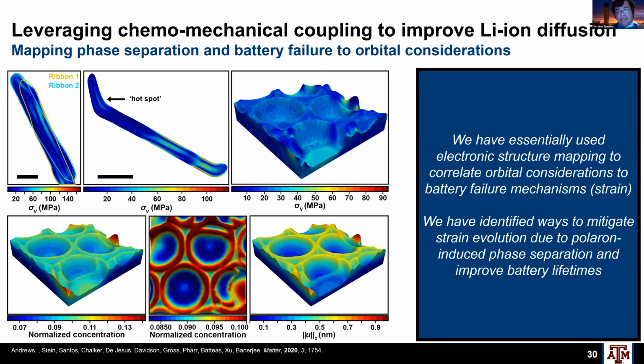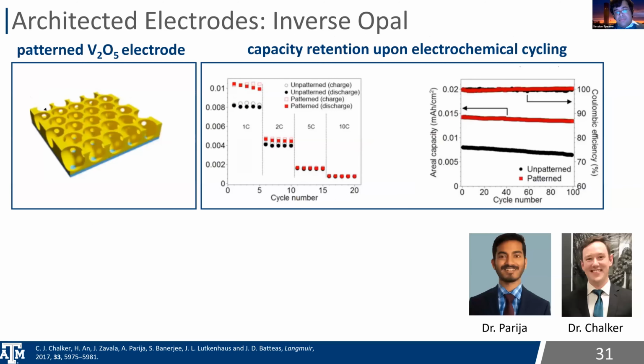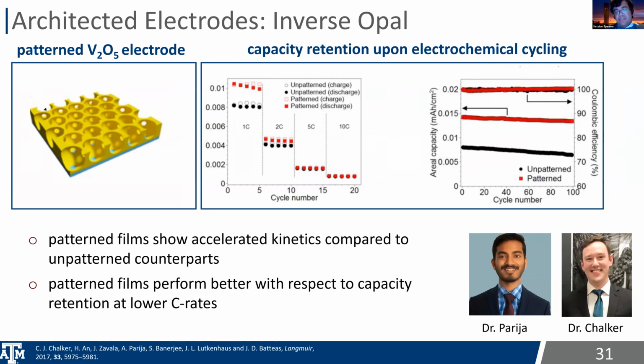And here are some images that also show the concentration maps we've been able to extract from STXM in conjunction with modeling, and that also translated to really fairly homogeneous strain stresses across the system. Okay, and not surprisingly, higher capacity as well as much better cycle life retention for these inverse opal electrodes, accelerated kinetics, and they perform much better with respect to capacity retention at lower C rates.